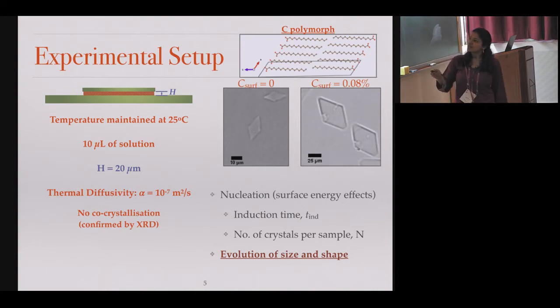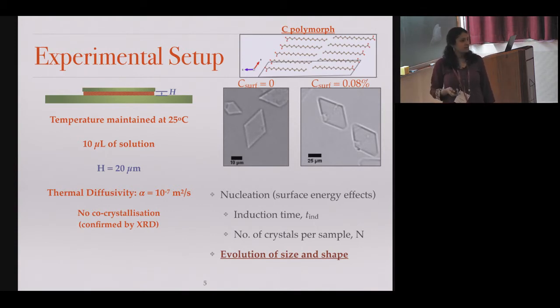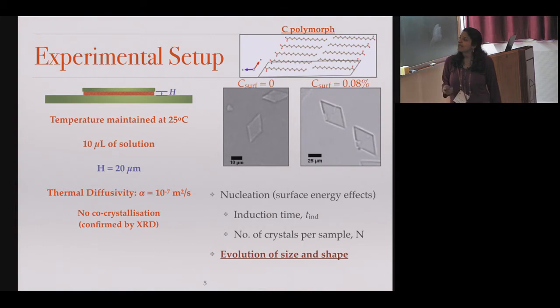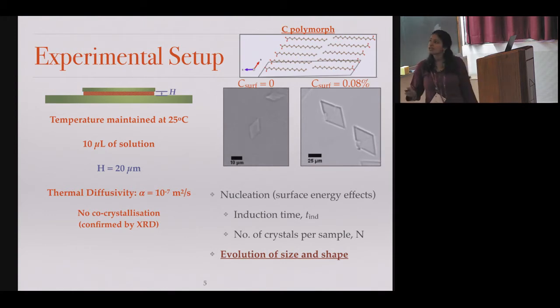The typical shape of a stearic acid crystal C polymorph is this rhombic platelet. We see that when there is no surfactant present, but when we add a surfactant, the crystal grows like a rhombic plate initially but then its shape deforms — you can see it by the edges getting flatter.